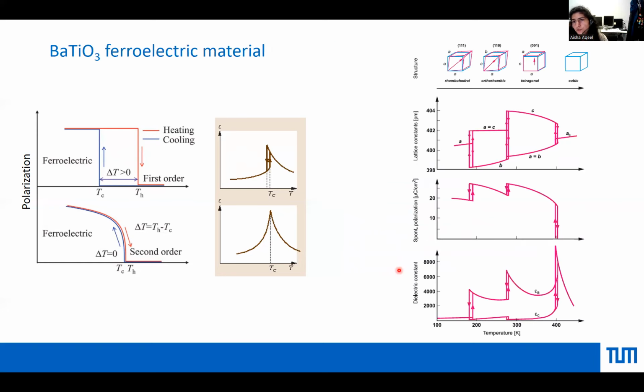An example of this is barium titanate, or PZT is also actually a good example of this. It's also a first order ferroelectric. So here is an example. The material goes from cubic symmetry, and then the symmetry gets lower and lower as you go down in temperature. So it is already ferroelectric here, but then there are some further transitions. And there is latent heat involved. You can see in all of them a hysteresis loop, and you can also see how the crystal structure is changing, and where the crystal structure is changing, the symmetry elements are also changing.